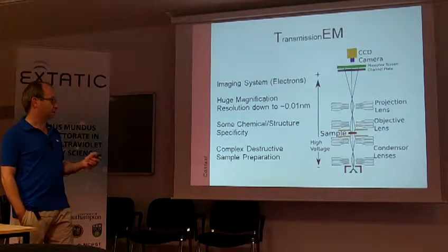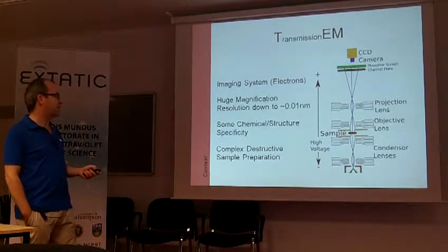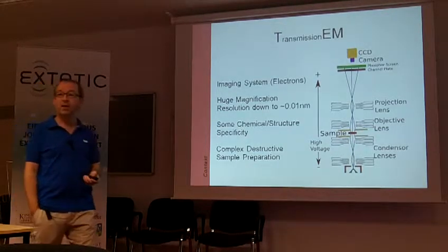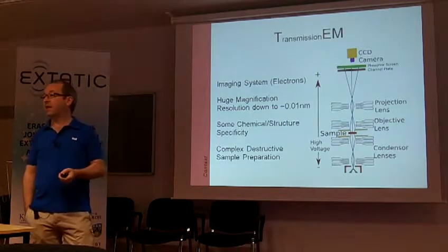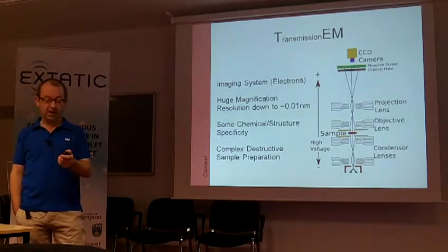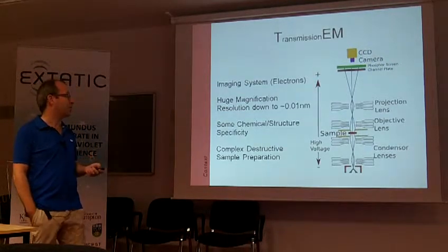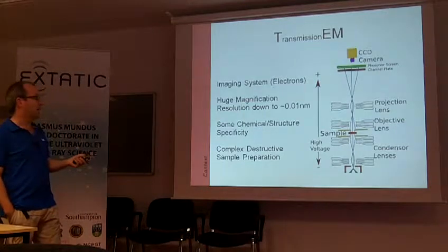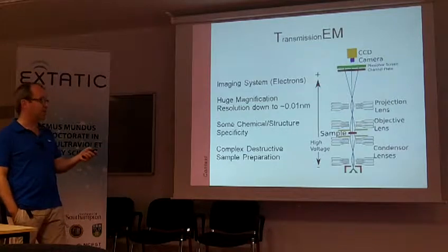And normally that contrast is driven by absorption, and for that you typically need high Z elements for the high energy electrons that give you the high resolution. So for a biologist, for example, they have to use osmium or gold staining in their samples, and they have to make their samples extremely thin. And this doesn't allow ready application of TEM at high resolutions to biology. And for semiconductor sampling, it's similar. You can't look at bulk samples with TEM.